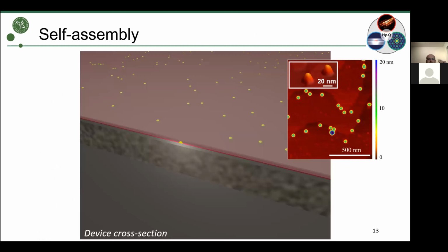So this is now an artistic view of how these quantum dots look like. Unfortunately, there is some drawback with the quantum dots, which is the self-assembly. Self-assembly means that the quantum dots nucleate randomly. So it's basically you're trying to grow a material that is not compatible with the substrate. Indium arsenide doesn't like to grow on gallium arsenide because it has a different lattice constant. So it prefers to nucleate into tiny islands, which are our quantum dots.